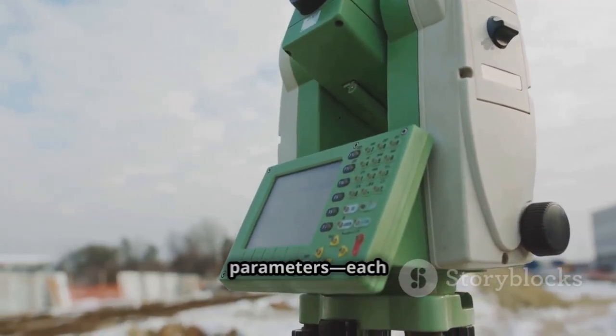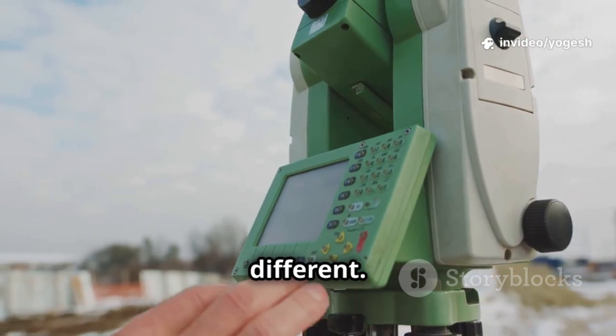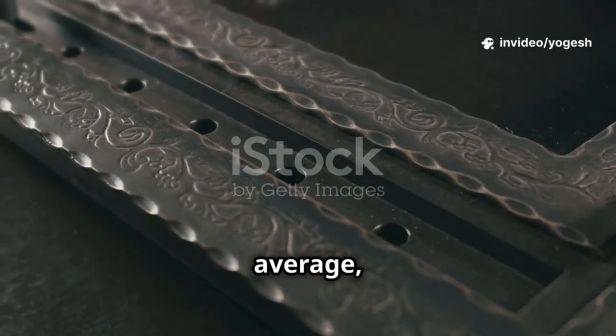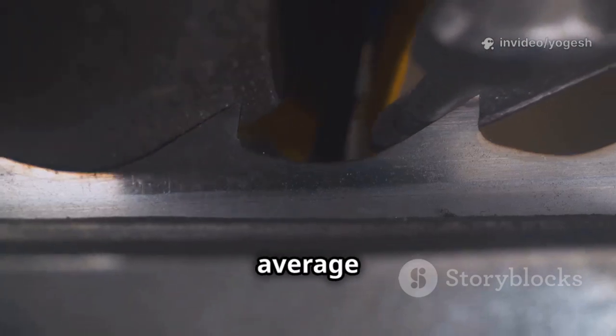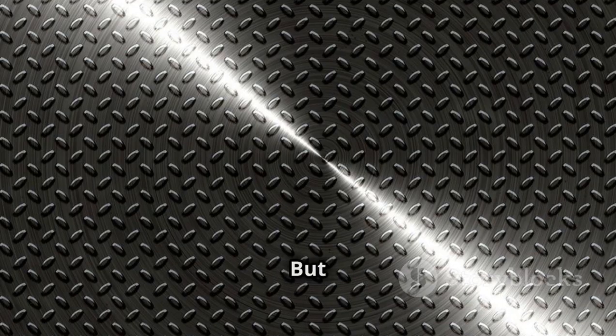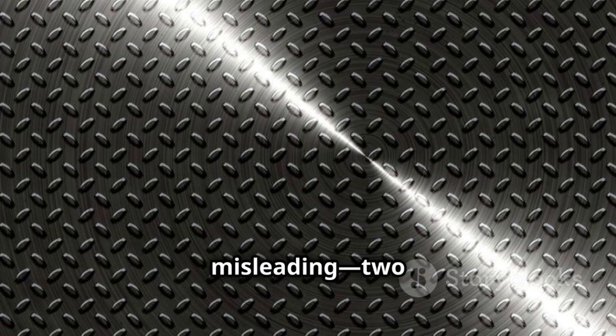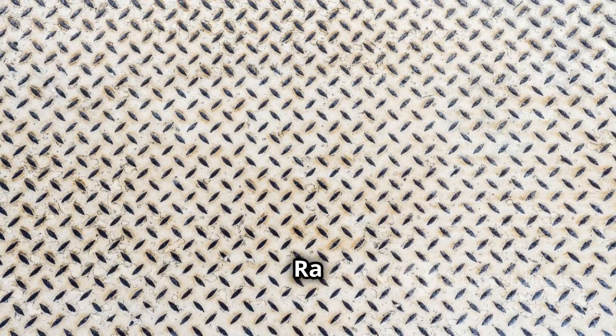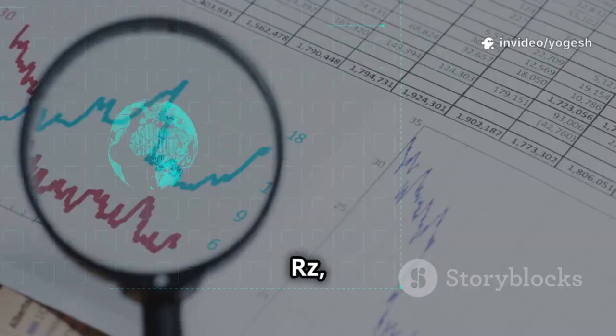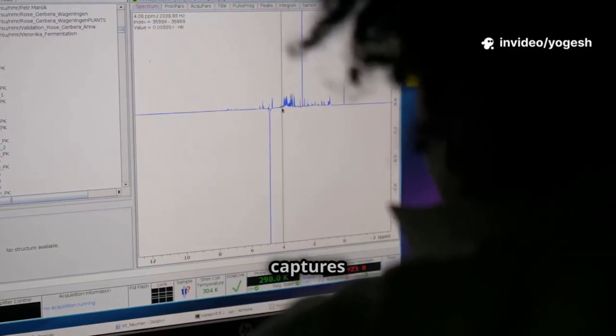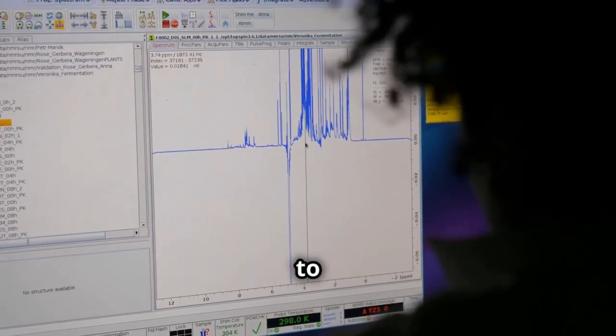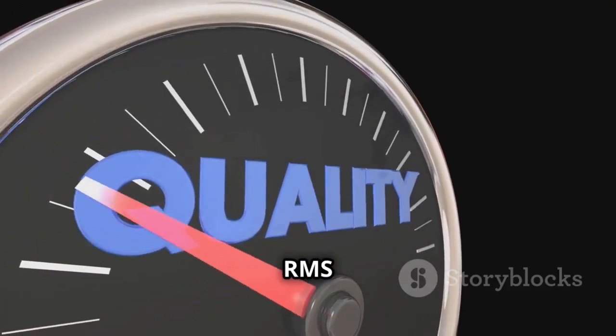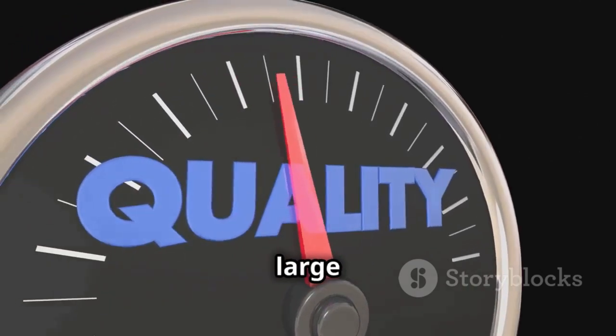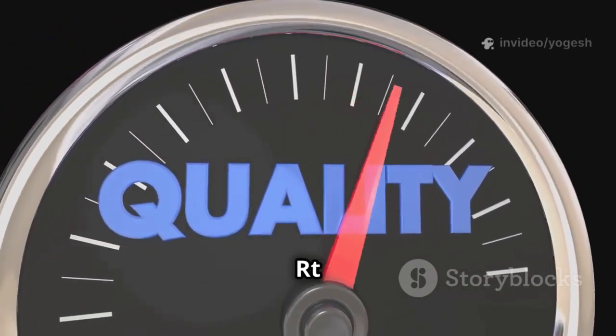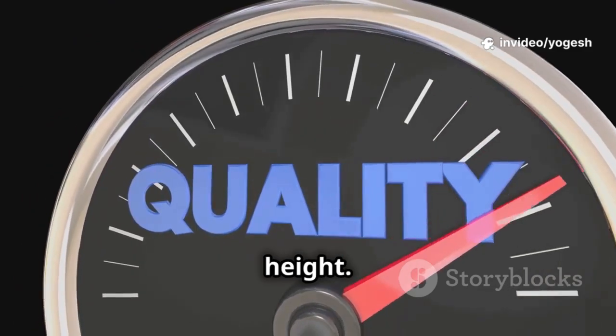Surface roughness is measured with parameters, each revealing something different. Ra, the roughness average, is the most common. It's the average height of peaks and valleys. But Ra alone can be misleading. Two surfaces can have the same Ra but very different profiles. Rz, the average maximum height, captures the distance between the highest peak and lowest valley, making it sensitive to outliers. Rq, RMS, gives more weight to large deviations, while Rt measures the absolute peak-to-valley height.